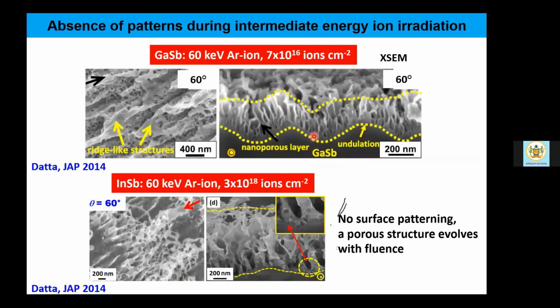Another interesting observation: pattern formation did take place in case of gallium antimonide, that science paper I told you, which actually gave a lot of boom to this field when they used a couple of hundreds of eV or tens of eV, I mean electron volt of argon ions. I mean both in gallium antimonide and indium antimonide. But when we enhance the ion energy from that kind of value of say 100 electron volt or 400 electron volt to 60 kilo electron volt, then we don't get to see any pattern formation. Instead, sponge-like structural evolution takes place, which are highly hydrophobic in nature and highly opaque for the visible light. Okay, so this is another important observation.